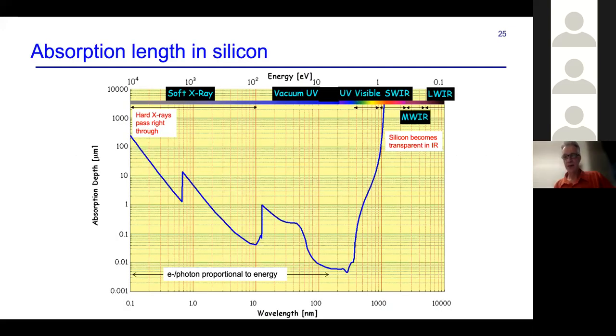So here is the absorption length curve across a very wide wavelength range. And so you can see your silicon detector actually can be used all the way from X-rays through to the near infrared. And we're interested in this little sliver down here at 100 to 300 nanometers, where the absorption length is at a minimum.